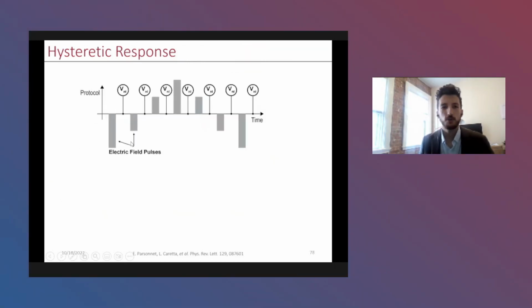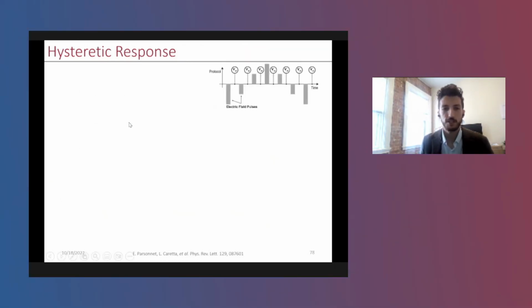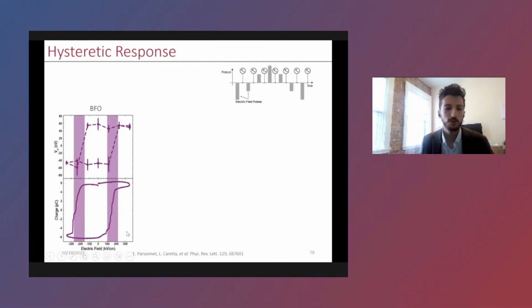In fact, we can do a hysteresis measurement where we measure the hysteretic response of the non-local voltage with an electric field, and we find that the coercivity of this hysteresis closely matches the polarization hysteresis loop. So indeed, the non-local voltage is switching with a polarization switch.